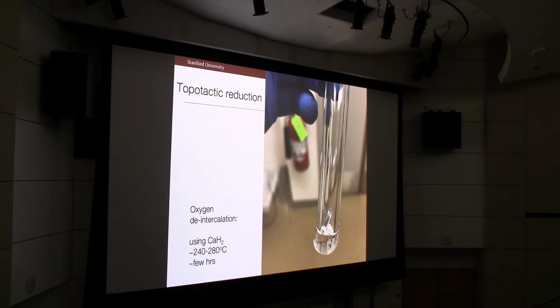It actually is. So for this deintercalation reaction, this is a small piece of our film, loosely wrapped in aluminum foil, and these pebbles are calcium hydride. So we're vacuum sealing this in glass tubes to pull out these planes of oxygen, so-called apical oxygen in the cuprate context, to form this metastable phase that we're going to study.